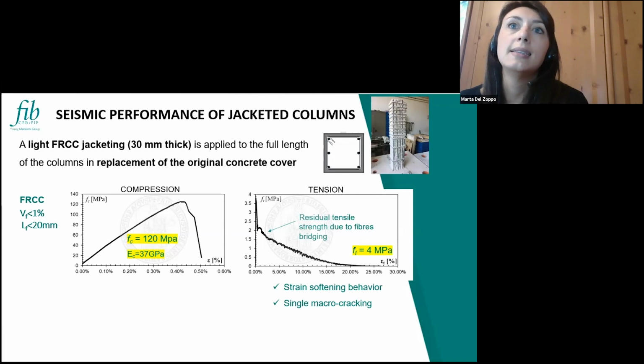These are the mechanical properties of the FRCC that we are adopting for this application. As I said, we have a high performance in compression, with a compressive strength of about 120 megapascal. And in tension, we have a peak strength of about 4 megapascal. And then we have this strain softening behavior, with the residual tensile strength that is given by the bridging effect between the fibers. For this material, we have a low fibre volume ratio, less than 1%. We are dealing with short plane fibers with length less than 20 millimeters.